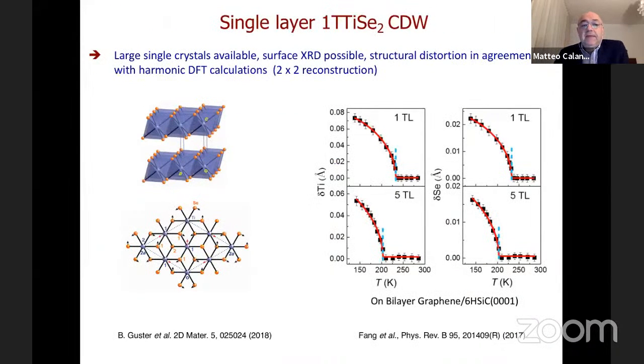So the single crystals of this system are so large in single layer form that it is possible to measure the atomic positions via surface X-ray diffraction. And indeed, we know that the charge density wave instability is exactly the one I showed you before. This is a somewhat more complicated plot, but it's the same that was shown before. And this has been measured also as a function of layers. For example, here you have 1 TL, where TL means tri-layer, that I call single layer, and this is 5 tri-layers, 5 single layers.